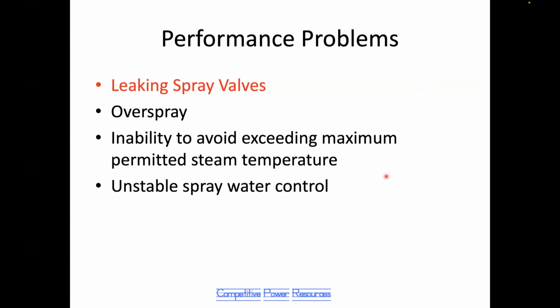Let's talk about leaking. This is the biggest problem, leaking valves. Then there is overspray, which means more water is sprayed into the steam than the steam thermally has the capability to evaporate. There's a difference in temperature between the steam temperature and the water temperature, and that difference drives the evaporation of the water droplets. If you spray too much water, you cool the steam all the way to saturation temperature, and now no more water can evaporate.